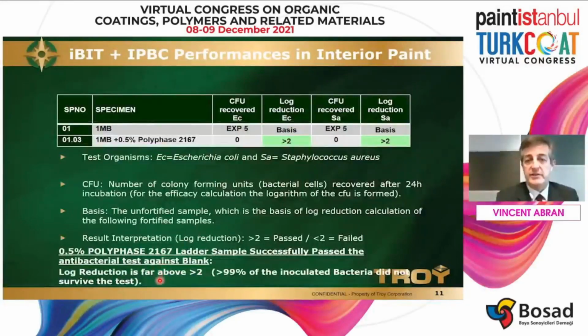Now we look here at the results. We have, for example, a blank sample. This is one paint here without any antimicrobial product. So this is an unprotected paint. Here we have Escherichia coli. So we measure a log reduction. We start from 10 to the 5th, and then we go down to 0. So we have a complete log reduction in this case, and more than 99% reduction of the bacteria survival, and then we pass the test. So this is exactly the point. We do that against Escherichia coli and Staphylococcus aureus here. And in both cases, we have a complete kill of bacteria within the 24-hour incubation.